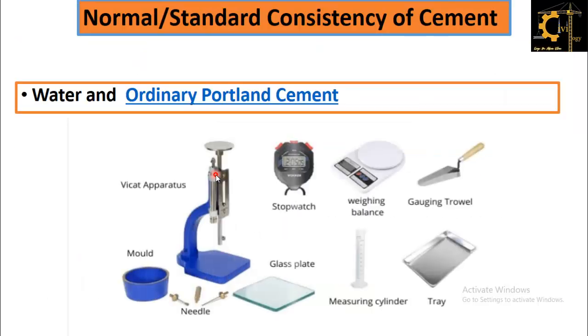And what materials or equipment are required for this test? As you can see over here, mainly it is the Vicat apparatus, and here is the assembly of the Vicat apparatus. It includes needles for initial setting time and final setting time, a plunger for the consistency test, a mold, and a glass plate. This glass plate should be non-porous and non-absorbent. We also need a measuring cylinder for the amount of water, and for weighing of cement we will use a weighing balance. A stopwatch is also necessary because we have to note down the gauging time. As I told you before, it should be 30 seconds.